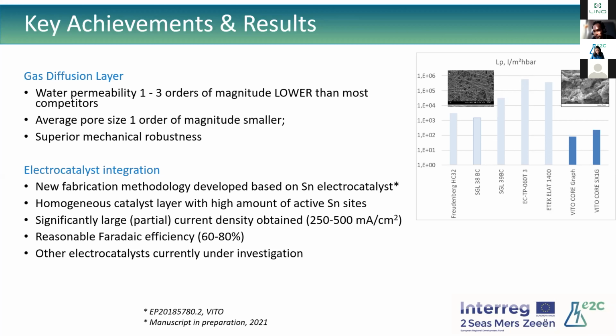So when we integrate a catalyst, there are, of course, several possibilities. I will not go into details here, but we worked on a tin electrocatalyst, and that's because the focus in this project is to work towards formate. And we developed a methodology to increase the amount of tin active sites and incorporate it in a homogeneous way in the gas diffusion layer, which realized relatively high current densities, around 250 and 500 milliamps per square centimeter, and also reasonable Faraday efficiency, 60 to 80%. Currently, we are working on other electrocatalysts. And if you go to the next slide,